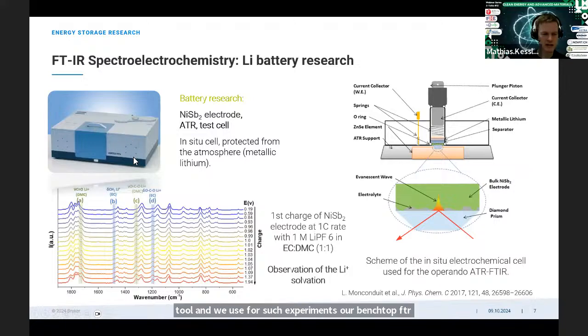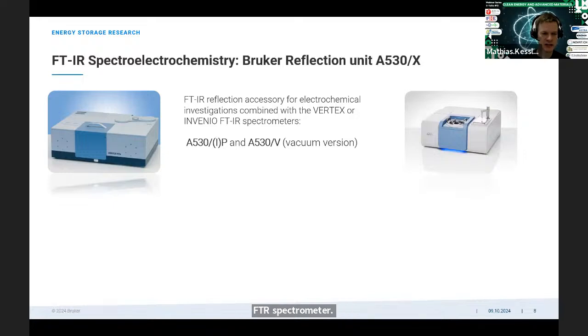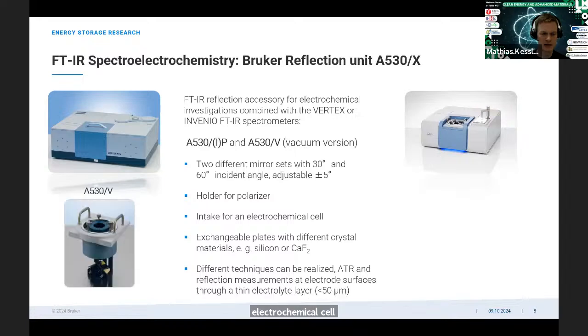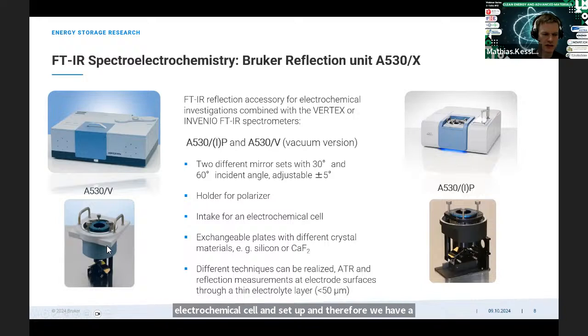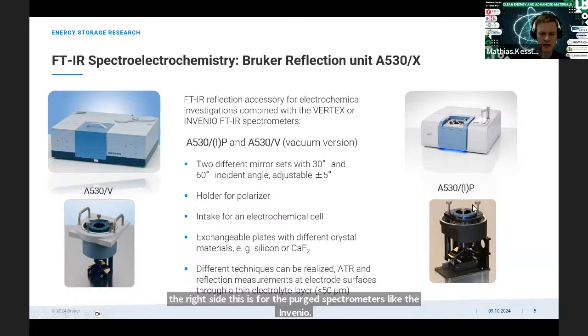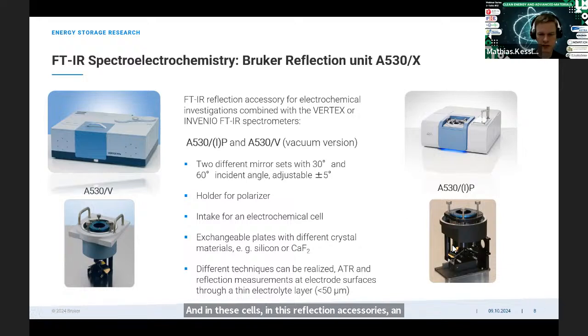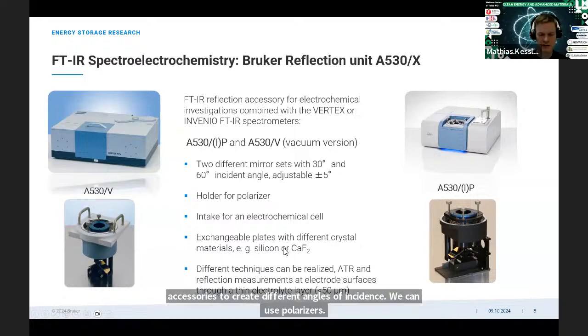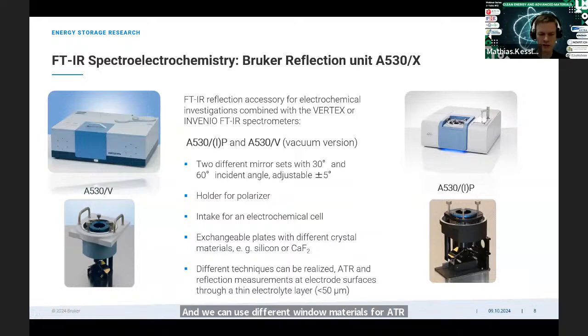So on the left side, you see our Vertex spectrometer, our vacuum FTIR spectrometer. What we need to do electrochemical reactions in an FTIR spectrometer, we need to include an electrochemical cell in the setup, and therefore we have a reflection accessory. You see it on the left side for the vacuum version, and on the right side, this is for the purge spectrometers like the Invenio shown here on the right side. And in these reflection accessories, an electrochemical cell can be introduced from the top. And we can then use different mirror sets in these accessories to create different angles of incidence. We can use polarizers, and we can use different window materials for ATR investigations, but also for reflection measurements on the surface of the working electrode. So different setups can be realized with this reflection accessory.